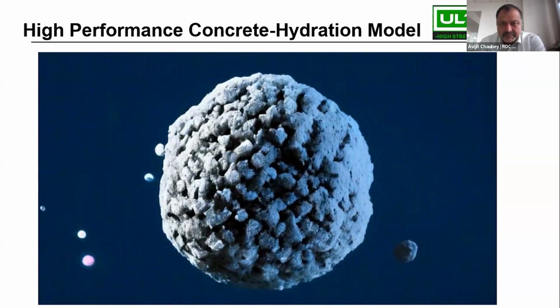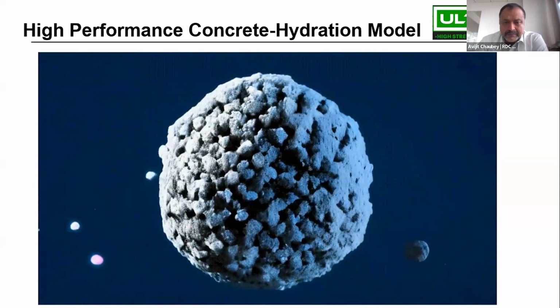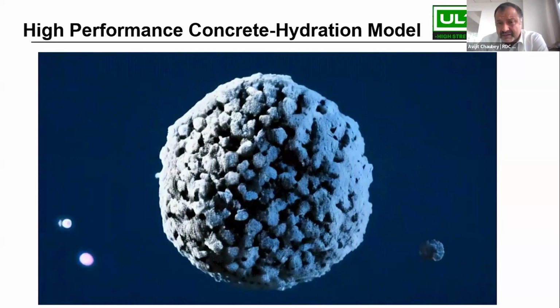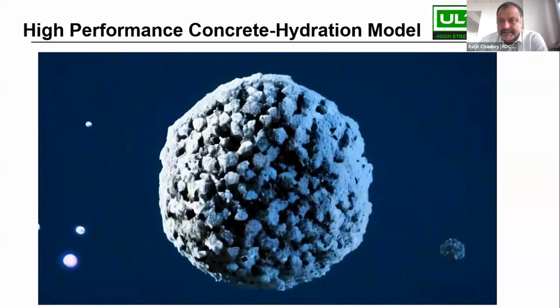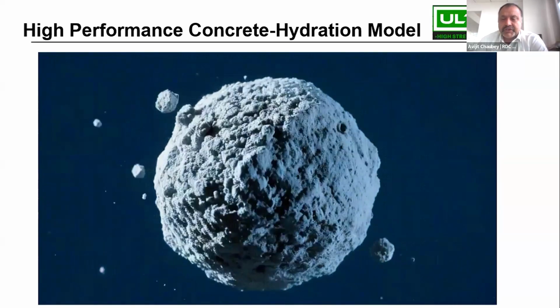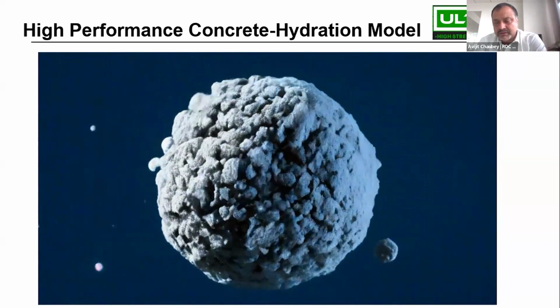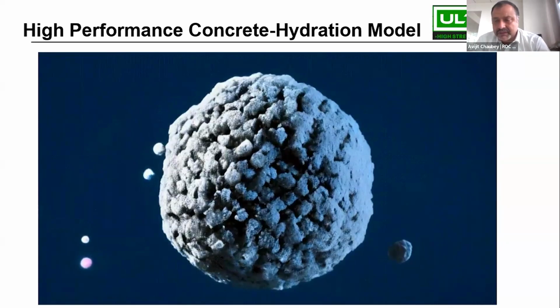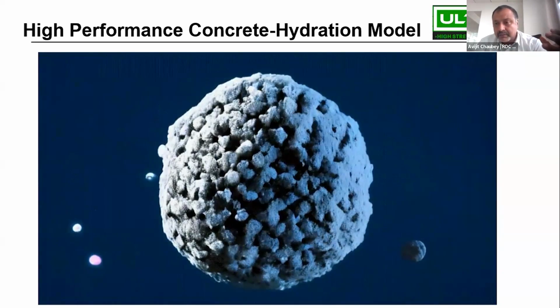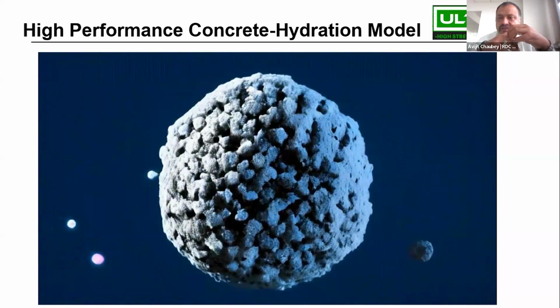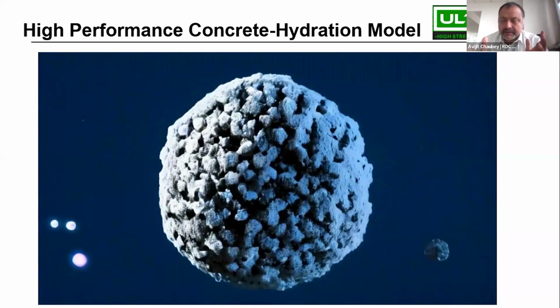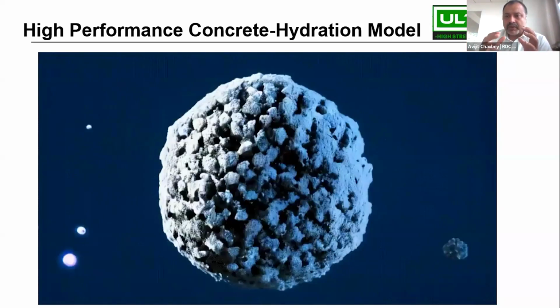So this is a model that I've tried to create. It was very difficult to make. What I'm trying to show is that when cement hydrates, the cement first starts dissolving in water. The particles coming out are the calcium ions and silicate ions, and they hydrate and form CSH gel in the water. They do not form it on the surface of the cement. So the biggest challenge in front of the designers is that this CSH gel, the material which gives strength to the concrete, has to precipitate on a hard surface. The only surface it finds is the cement particle, and it keeps precipitating on the cement surface.